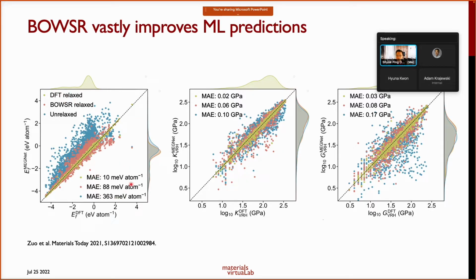And what we show is that when you actually have unrelaxed crystal structures, the predictions from your machine learning algorithm are disastrous, right? The errors are very, very large. In some cases, they are so large that they are useless for even stability predictions. Once you apply the BOWSR algorithm, you can get a much lower error. This is still not ideal, but it's definitely much better than 363 meV per atom. And of course, DFT is expected to perform the best, right? So that's not surprising.